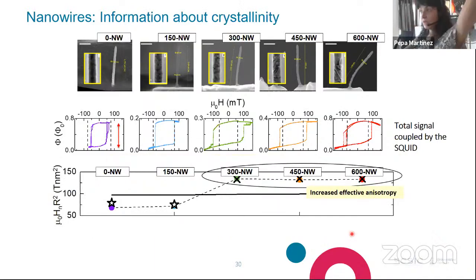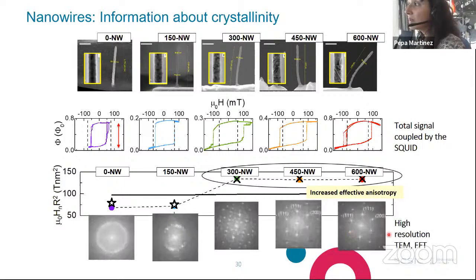There were much more things that we could tell from these measurements, but I don't want to go too much in detail about that, but let me just mention that we could also verify that the anisotropy and therefore probably the crystallinity of this composite was being increased with annealing temperature. Okay, this was also verified by these high resolution TEM images that you see here below. This first picture here corresponds to the not annealed nanowire, where you can see that the structure is almost amorphous, whereas the nanowire annealed at the largest temperature exhibits these very nice Bragg diffraction peaks that correspond to a very nice crystalline structure.